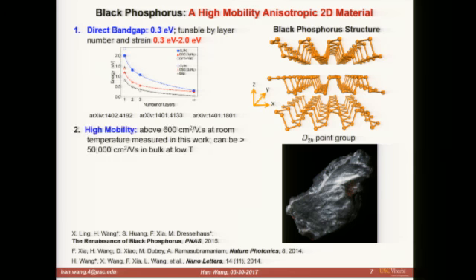The material is also pretty decent electronically. In our first work, we measured the hole mobility at room temperature around 600 centimeters squared per volt second. At low temperature, in the bulk form, literature reports above 50,000 mobility. Nowadays, the room temperature mobility can easily exceed 1,000 in black phosphorus-based materials.